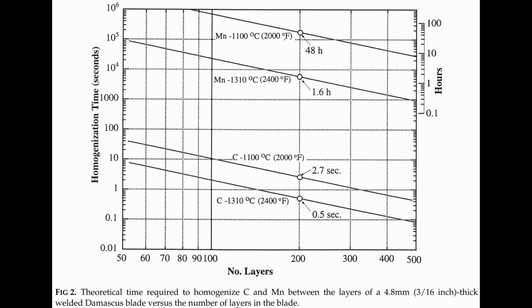So here is a study done by Howard Clark and John Verhoeven, where they did some estimates using simulations, computer models, to look at how long it would take for carbon to fully equalize in Damascus with different layer counts. And so they found with 2,000 degrees and a 200-layer Damascus, that's 3/16 thick, that it would take 2.7 seconds for the carbon to equalize in the steel, so very fast.